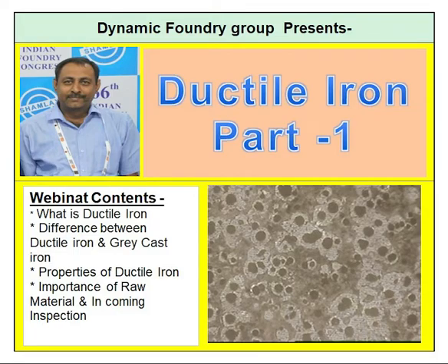Annealing of ductile iron, as I told you earlier. In the old days it was done that if your hardness was not achieved, you can convert that into ferritic grade by using annealing. Annealing is the heating of the casting to a certain temperature, say 920 or 930, and then slowly cooling it, and then the matrix changes from pearlitic to ferritic. So that is the annealing cycle.